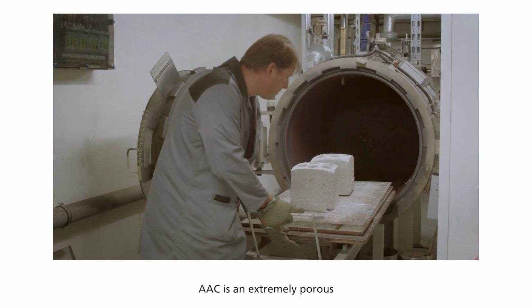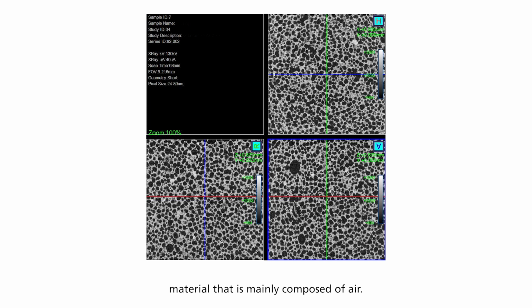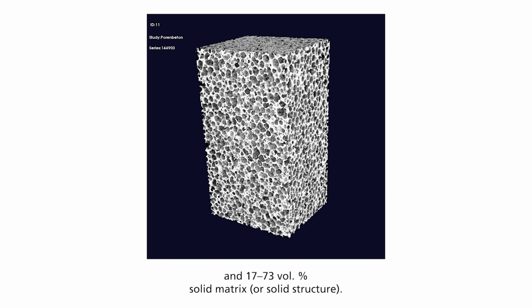AAC is an extremely porous material that is mainly composed of air. This fact provides its main favorable property, especially the excellent thermal insulation property. In general, the AAC volume is composed of 27 to 83% volume of air pores and 17 to 73% volume of solid matrix, or so-called solid structure. The air pores are generated due to the reaction of aluminum powder under an alkaline condition and the formation of hydrogen gas as the reaction product, which generates the air pores.